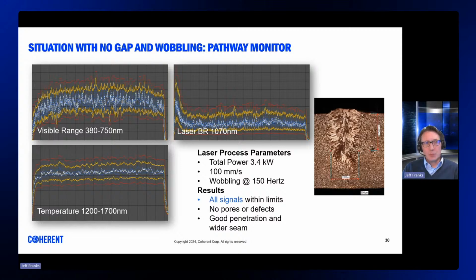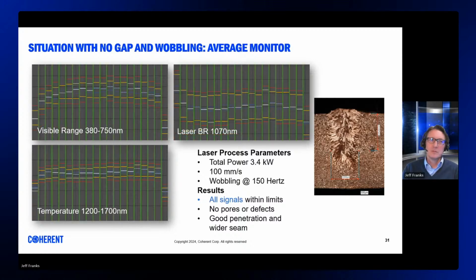Now, we see how the process monitoring handles the more challenging dynamic beam wobbling process condition. This increases the overall process window, no doubt, but also generates a wider band of pathway data due to the increased noise, which means that SmartSense Plus needs to be adapted for the warning and error condition limits accordingly. By applying the average monitoring filter to the noisy data, as we mentioned, we can provide more stable monitoring of the process.